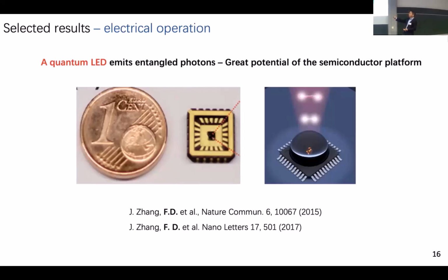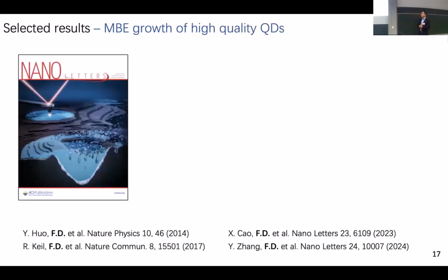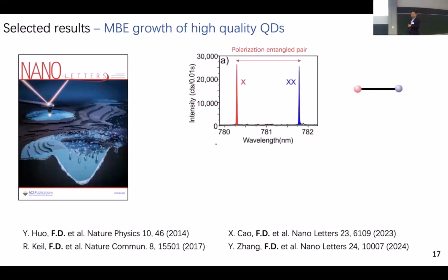This is a good example to show the potential of this system. And we also do a lot of MBE growth, okay? So this, for example, shows the spectrum from one single quantum dot. The quantum dot looks like this. In the aluminum gallium arsenide substrate, we use the so-called droplet epitaxy to remove some of the material and make a hole. Then we fill gallium arsenide inside, and finally we cap it with another layer of high band gap material. So this is our quantum dot, okay?